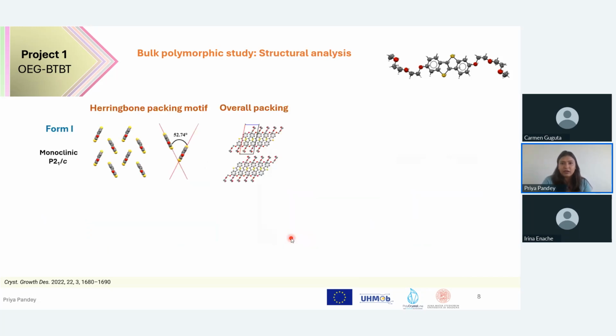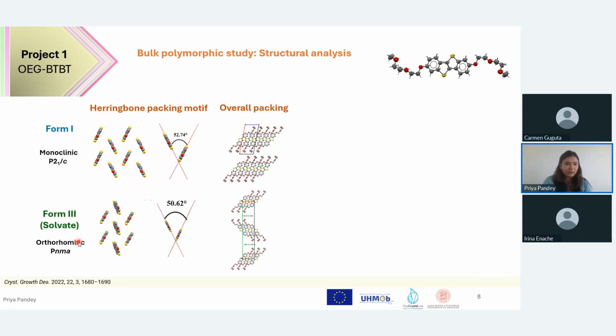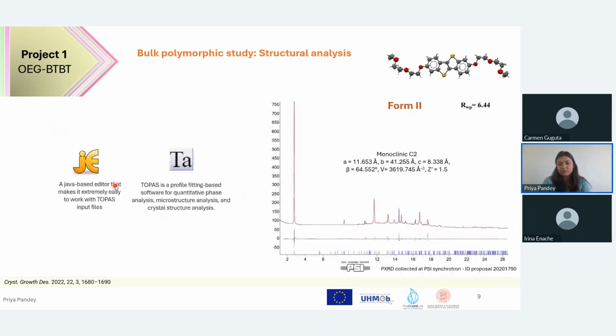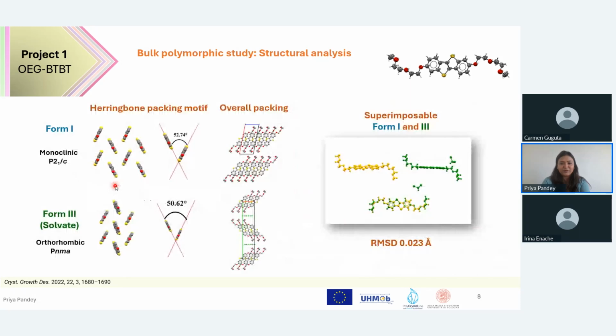Then comes the structural characterization. As I mentioned, with the methods of obtaining crystals, we can obtain crystals and then finally solve them by single crystal XRD. I solved form 1 crystals, and I also obtained form 3, which was a solvate in dichloromethane. If we look at the packing of these 2 polymorphs, I'm sorry, my cursor is moving too fast. If we look at the packing, we see that the BTBT molecules are arranged in a herringbone packing motif.